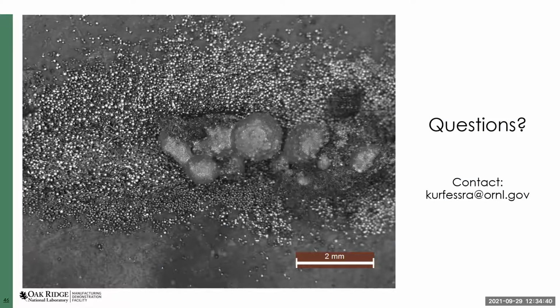Yeah, so I did test some pure polymers. I tested neat PLA, which is just a polymer. And then I tested some polymer composites, so usually 10 to 20% of some kind of filler material, such as glass fiber, carbon fiber, or in the case of the material you're talking about, wood flour, which isn't really a fiber. I just wanted to see the effect of the wood flour versus a neat or unfilled PLA.